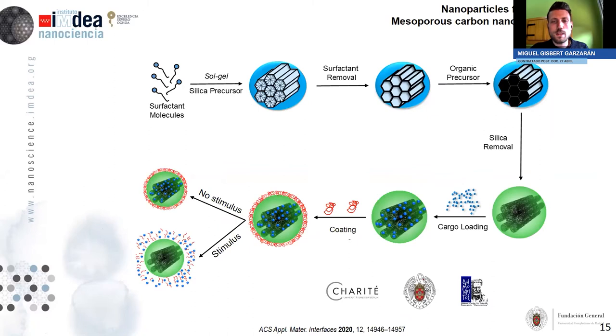So far we have demonstrated that we have this self-immolative technology that can be used to close the pore entrances. So after that, and because I did my thesis in the framework of a European project that involved the use of carbon nanoparticles, we tried to translate such technology into the carbon nanoparticles. So the idea of the project is basically the same. We wanted to synthesize nanoparticles, load them with a payload, coat them with a self-immolative polymer, and check whether there is release or not in the absence or presence of a stimulus.